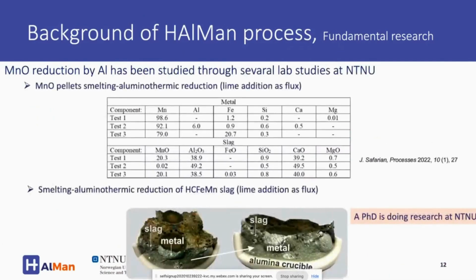Here you see some typical products. On the table, you see that we can produce manganese with high purity, over 98% purity, and also we can produce manganese aluminum alloy, which is quite new. We call it in the project aluminum manganese. So aluminum or manganese is the dominant or second minor component, but we can play with the quantity of aluminum in the metal. And also we can produce products like ferromanganese, low carbon ferromanganese, or ultra low carbon ferromanganese. And in parallel, we can produce slags with low manganese oxide concentrations.